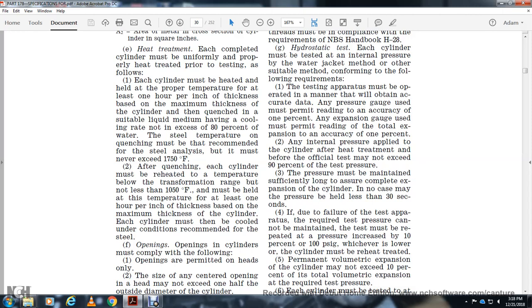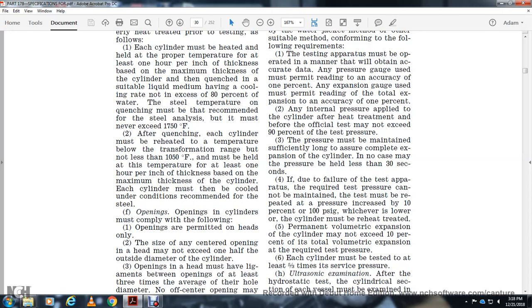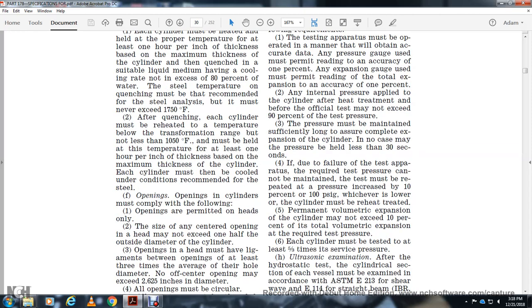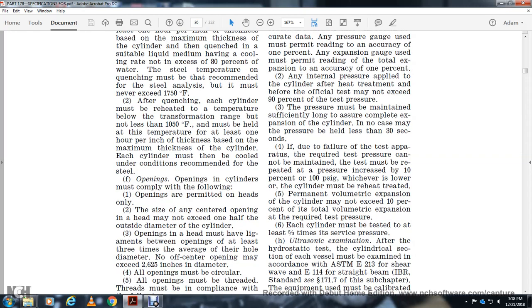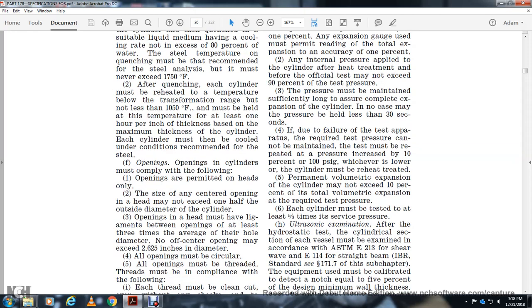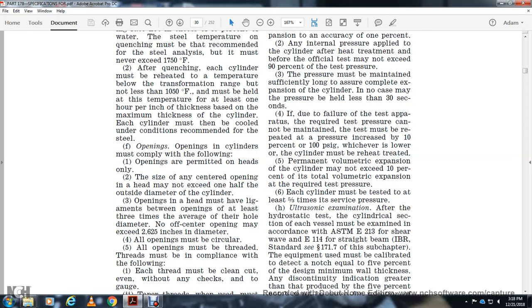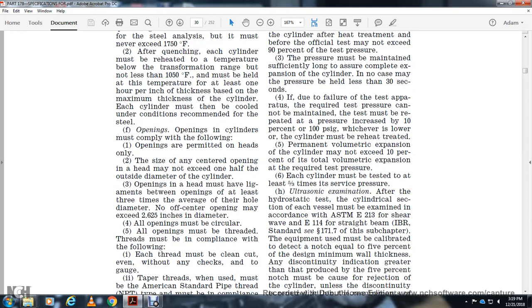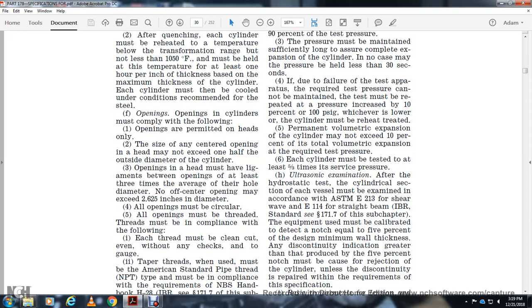Permanent volumetric expansion of the cylinder may not exceed 10% of the total volumetric expansion required, and the test pressure of each cylinder must be tested. Ultrasonic examination: after the hydrostatic test, each vessel's cylindrical section must be examined in accordance with ASTM E213 shear wave, E114 straight beam, and the equipment used must be calibrated to detect a notch 5% of the design minimum wall thickness. Any indication greater than that produced by the 5% notch is cause for rejection, unless the discontinuity is repaired within the requirements of this specification.